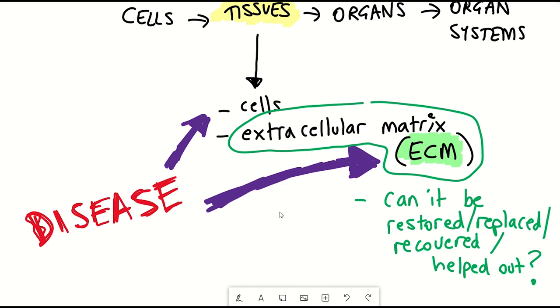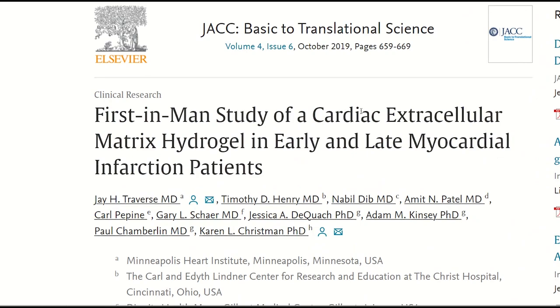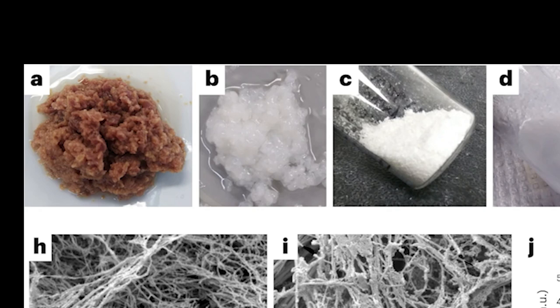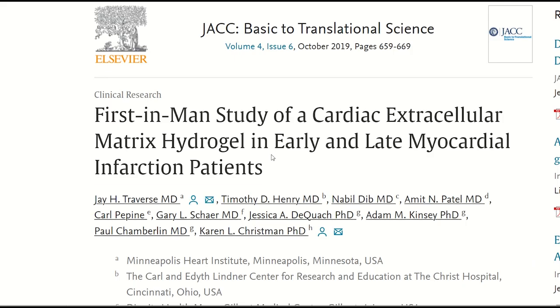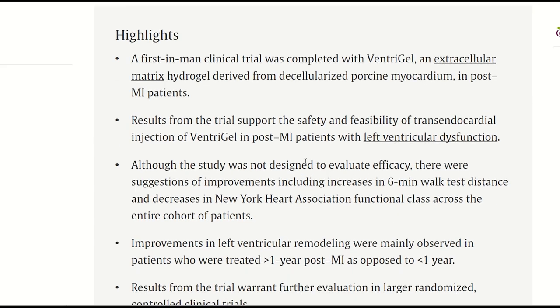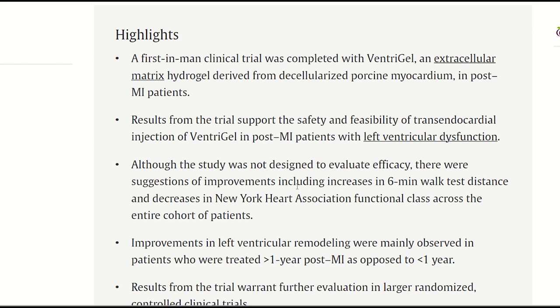Well, at least for the former, this has already been tested in humans, using ECM biomaterial — effectively isolating components of the ECM from tissue samples, removing all the cells, doing some digestion and fractionating the sample, and then injecting it back. In this first-in-humans study, to determine the safety and feasibility of this approach, 15 patients who sustained moderate damage in their left ventricle wall following a heart attack received a self-assembling ECM developed by Karen Christman and colleagues that remains liquid at room temperature, yet formed a gel at body temperature.